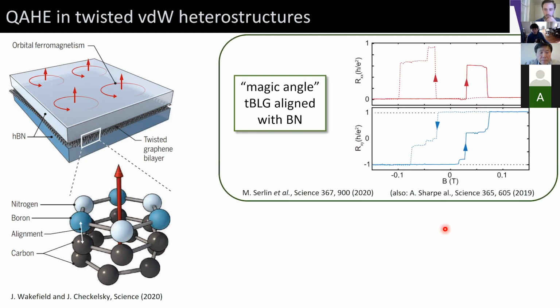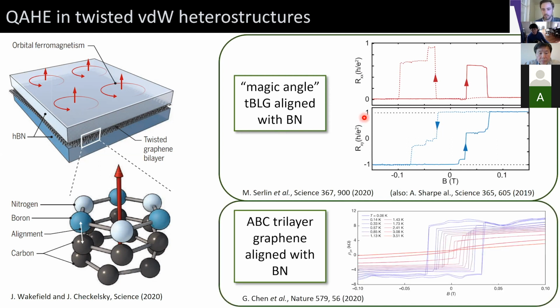So just as a bit of historical overview from things over the past few months, in samples of magic angle twisted bilayer graphene further aligned with boron nitride, there was a fully quantized quantum anomalous Hall effect that was realized with Chern number of 1. In rhombohedral or ABC stacked trilayer graphene, also aligned with boron nitride, there is a still developing but nearly quantized quantum anomalous Hall effect with Chern number of 2.